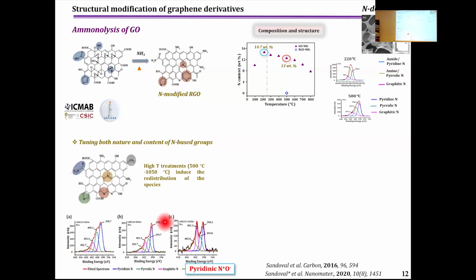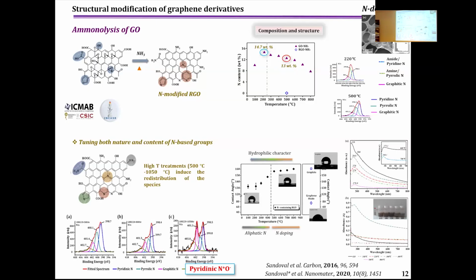We also create a new group, pyridinic N-oxide, which, as we will see later, also provides new properties to the material we have synthesized. Depending on the nature of the nitrogen that we introduce inside the system, we also change the hydrophilic character of these materials. Taking graphite as reference, materials with covalent groups attached to the surface, let's say amines and amide groups, show a larger hydrophilic character compared with nitrogen atoms which are introduced in the conjugated system of graphene. And we also improve the dispersibility in water of the material that we prepare using this ammonolysis approach.